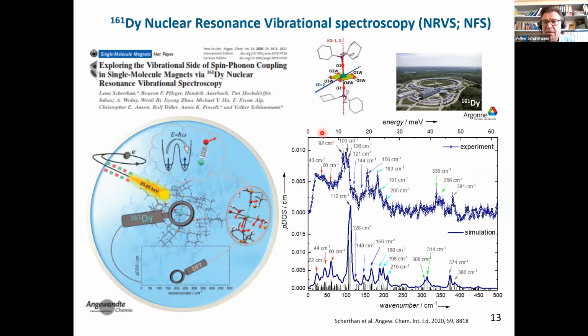Now we were also, of course, hunting for vibrations, and that came some time later. With the same complex here, we could measure the NRVS or NFS pattern, and this is data here obtained at roughly 20 K, and we could simulate this data with a density functional theory approach so that we could assign almost every mode we could see.